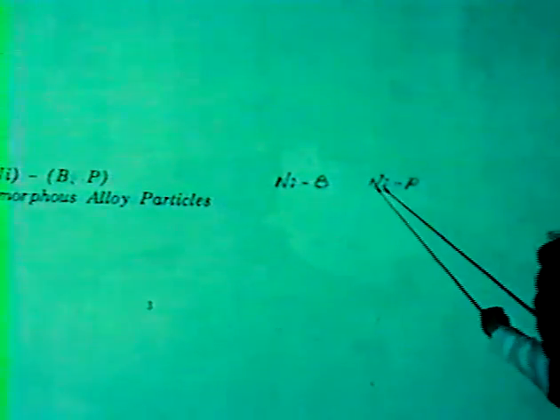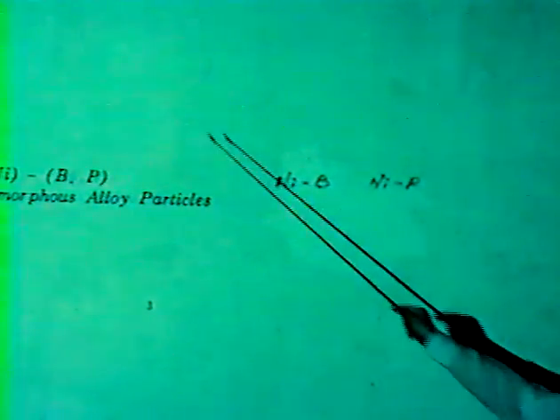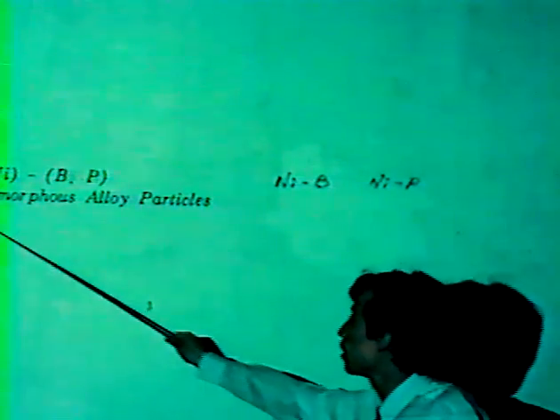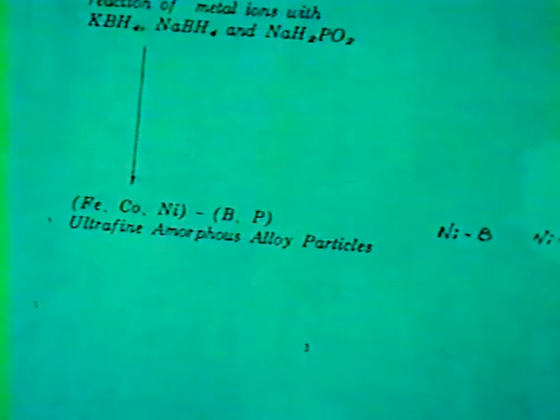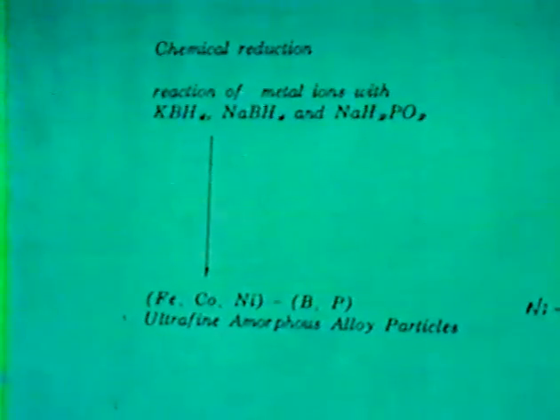Recently, we have reported that the nickel boron and nickel phosphorus samples prepared by this method are actually ultrafine amorphous alloy particles, and because of the combination of amorphous structure and ultrafine particles, these samples show higher activity than their ribbon alloys. Here I report some results on the hydrogenation of carbon monoxide on this catalyst.